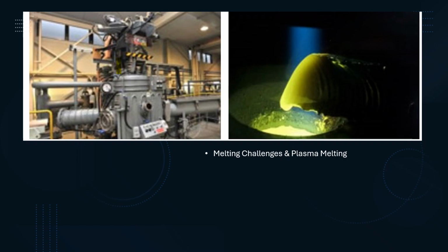The biggest challenge is melting and forming due to the 2,446 degrees Celsius melting point. Standard furnaces can't handle it, so specialized methods are required. Plasma melting furnaces use ultra-hot plasma arcs exceeding 5,000 degrees Celsius to melt iridium while vaporizing residual impurities. Companies like Furuya Metal use double plasma melting for high purity ingots.